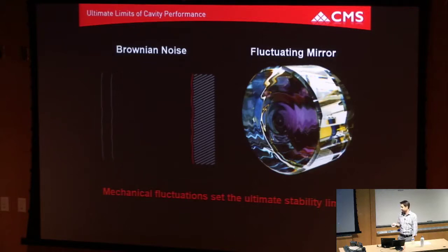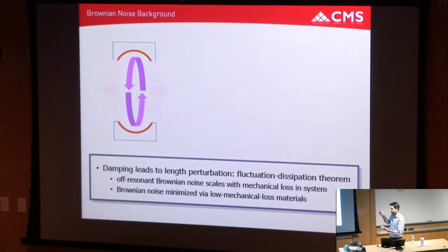And actually, the magnitude of the Brownian motion, in terms of its frequency dependence, depends on the mechanical loss angle or the mechanical quality factor of the body. And this I'll make some more sense of here. So if I take one of those Fabry-Perot reference cavities, and I didn't mention this earlier, in the clock system the thermal noise impact is somewhat indirect. Ultimately, you want your laser line to be as narrow as possible to interrogate this atomic transition, and you'd like that laser linewidth to be even narrower than the natural linewidth of your atom. What you do is you take a somewhat noisy kilohertz linewidth laser, and you stabilize it against an ultra-stable etalon, an ultra-stable reference cavity.